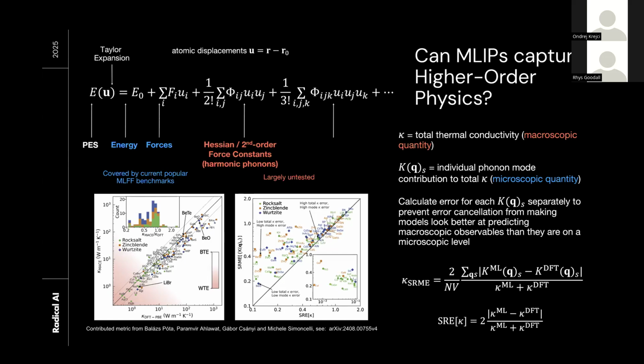Yeah. No, my only question is because sometimes there are some problems with the calculations related to layered materials, in which for the lattice thermal conductivity you have different values in the in-plane and in the layered direction. And several calculations that exist do an isotropic lattice thermal conductivity, which should sometimes be carefully taken care of. And I've seen papers that do not consider the anisotropic effect. Yes, exactly.